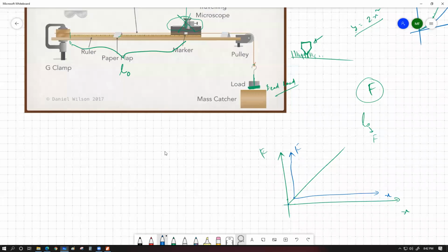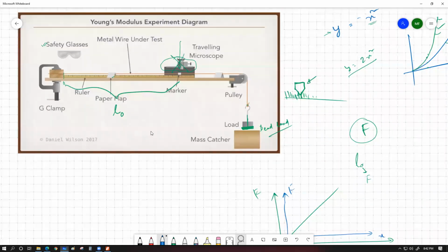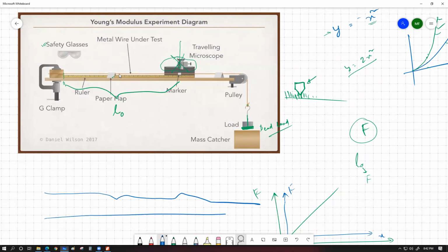Here comes another precaution that just popped in my head. Another precaution for this experiment is that before we attach the whole wire onto this setup, we must make sure that the wire is perfectly straight all through. So the wire should not have kinks or bends in its body, something of this sort. The wire should be made perfectly straight. And how do we make a perfectly straight wire? By usually pulling it across a sharp metal or wooden edge, and you have to just pull it.